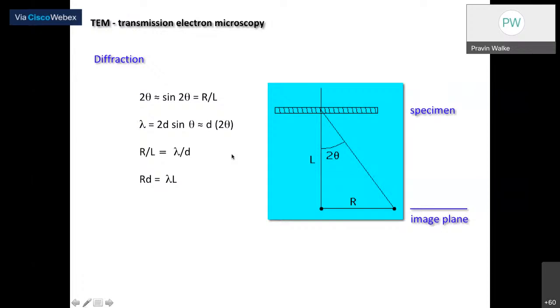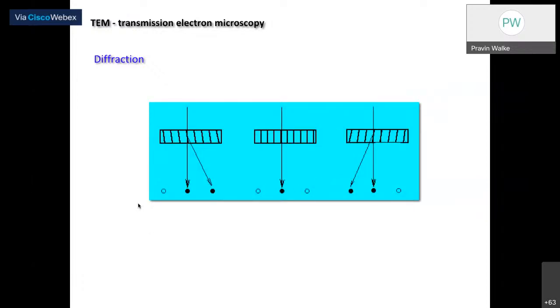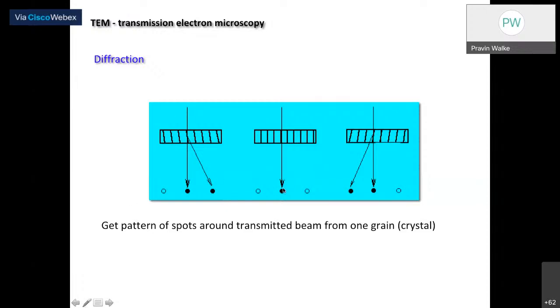So how can someone find this particular interplanar distance, for example this d value? Here is the formula, right? Lambda equals 2d sine theta, and we find R/L, where L is the camera length, right? This is the specimen, and this is the screen, and that distance is the camera length. In the scattered diffraction pattern, you find different spots, and the spot distance from your straight camera point here can be measured, and from that you can easily find the d value, because you know the L value, you know the 2 theta value, and you know the R value. So we can find the interplanar distance between these two spots, right? These interplanar distance calculations will give us information about the planes, the arrangement of the atoms, and structural information of your material. So here are the different important diffraction things.